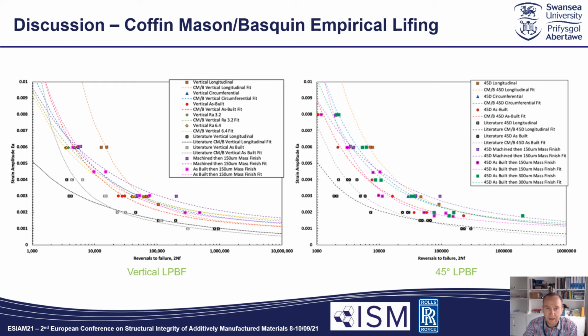Although lacking in the elastically dominated high cycle fatigue range, we did take some values from literature, as given by the darker coloured series, and they match up with the plots quite well, which of course, again, is quite pleasing. Of course, though, caution does need to be taken before jumping to any kind of bold conclusions, and tests would still need to be carried out, particularly under the HCF conditions, to flesh out these curves a little, but the fits do look very promising indeed.